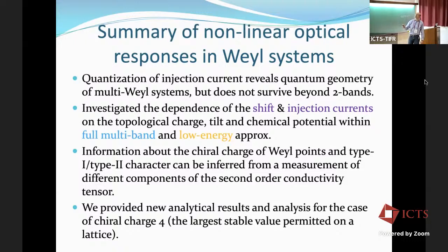We can use the results that we have for the shift and injection currents with light that's incident in various directions to infer the topological charge of the Weyl points, the tilt, and the chemical potential, which is particularly advantageous for some materials which may not have good photoemission characteristics. So photoemission requires very clean surfaces and some other constraints on the material. Optical conductivities and these sorts of experiments, these currents, are easier from the point of view that they're more applicable to a broader class of materials, so you can still get photoemission-like information using this strategy.